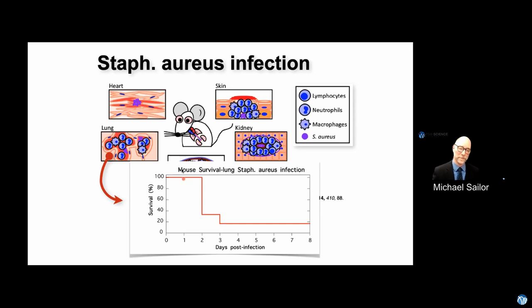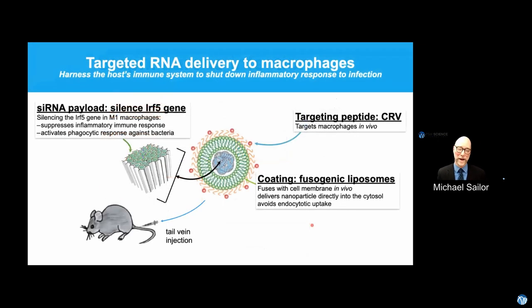So again, what I'm showing here in the bottom chart is what we call a survival curve. If mice are infected with this in their lungs, after a few days, they all die away. So 100% survival means they're all alive, and by the time you get to zero, if you have a few left over at the end, their immune system has kicked in and they've survived that challenge. What we wanted to do is figure out how to allow the immune system to respond but not over respond, to be able to fight off that infection. In our approach, the focus was on dialing back that highly inflammatory response of the macrophages.